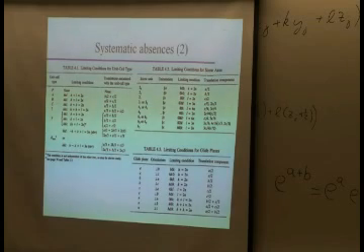Because what they care about is what do you see. Now for the math part of it, you can deal with what am I going to see. All that you can derive mathematically is what do you not see. Okay? So that is why you have limiting conditions in some tables, but you talk about systematic absences in many cases. Because let's face it, the program is not going to look at things and say, oh, I see a reflection. The program is going to say, this is my unit cell. What are the reflections I don't see that should be there according to this unit cell? Okay? So, systematic absences, limiting conditions, really just two ways of looking at the same beast.